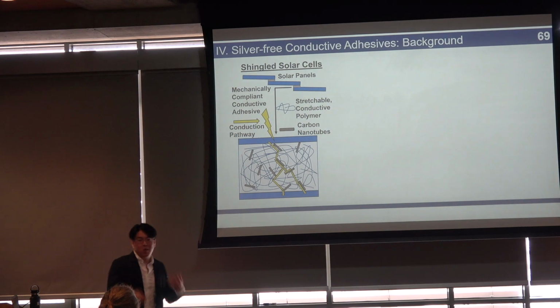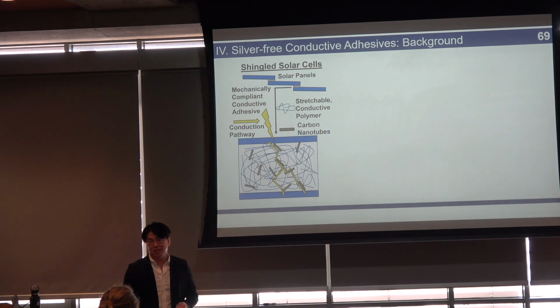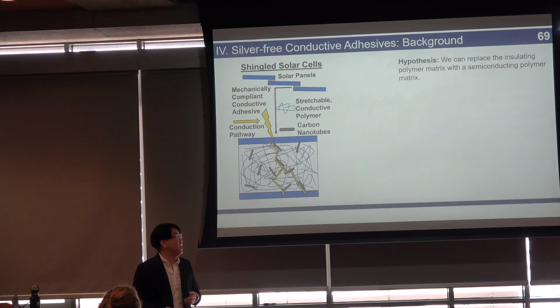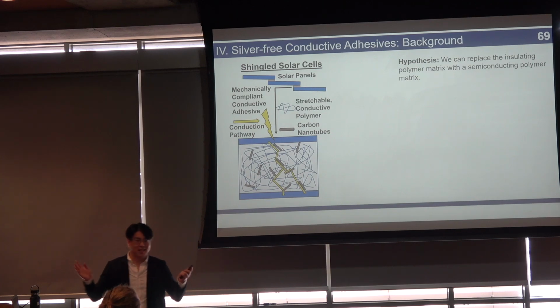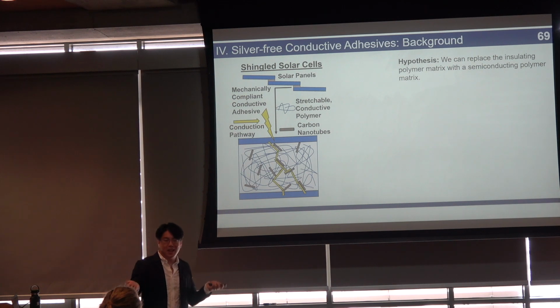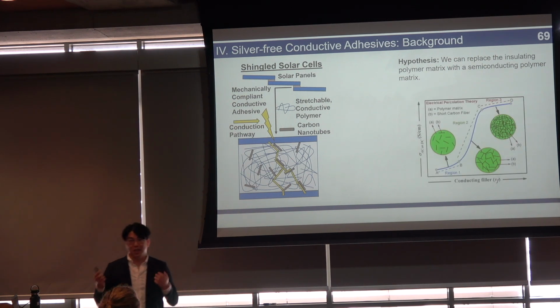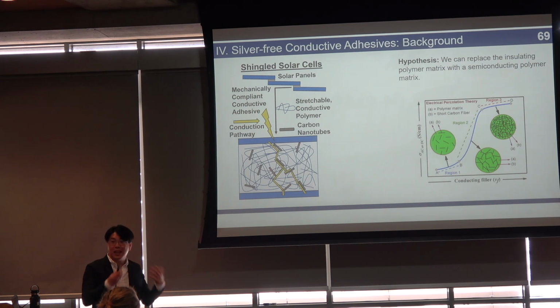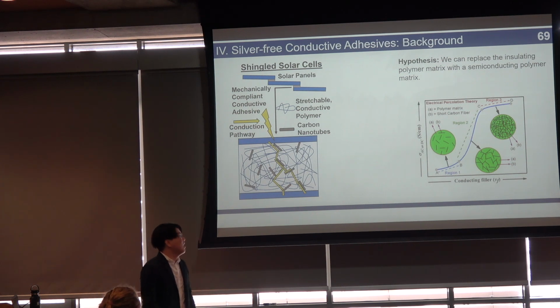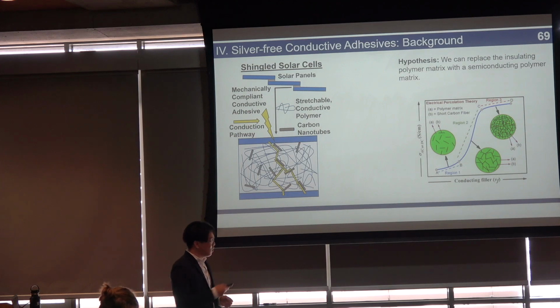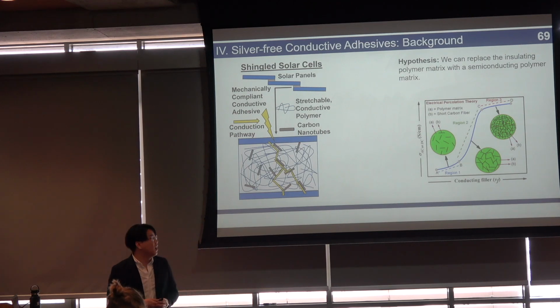So how can we design our way around this, right? This is sort of where semiconducting polymers can come into play. Our central hypothesis is, well, what if you didn't have an insulating matrix? What if you replaced your insulating matrix with a conducting matrix? If you replace it with a conducting matrix, you need to add less things to make it conductive. You increase the electrical percolation pathways that are in your glue, and you don't need to add very much stuff.